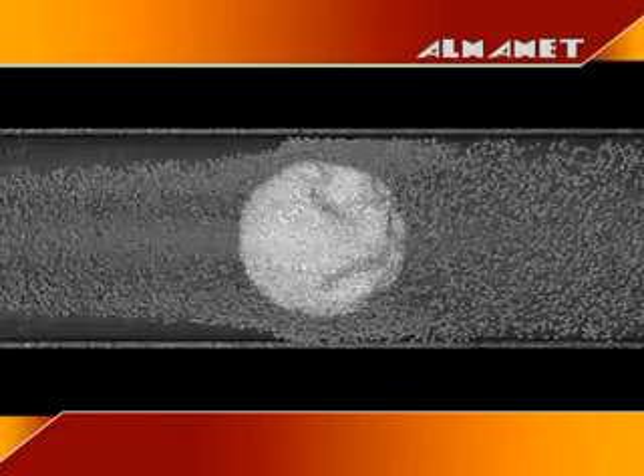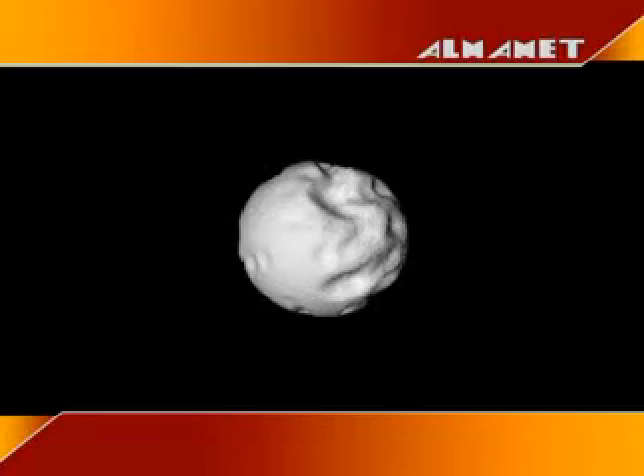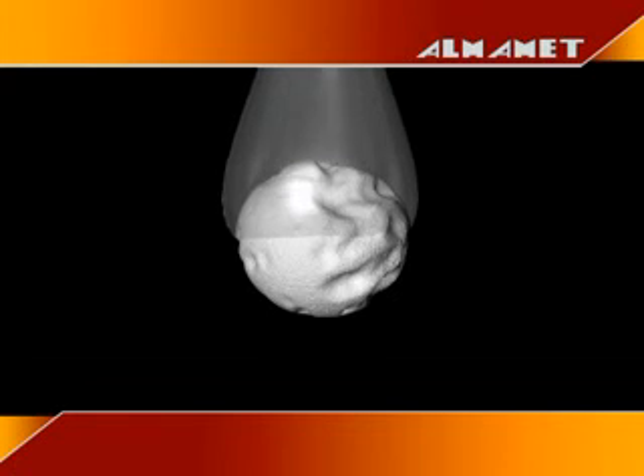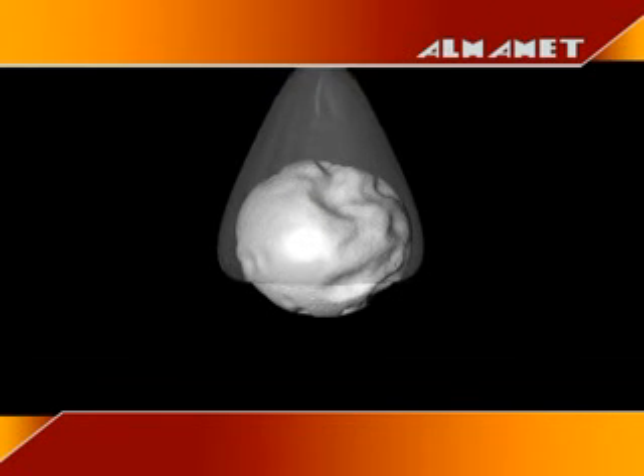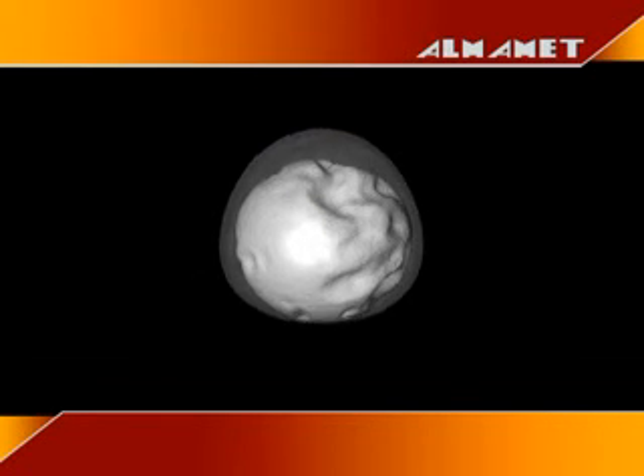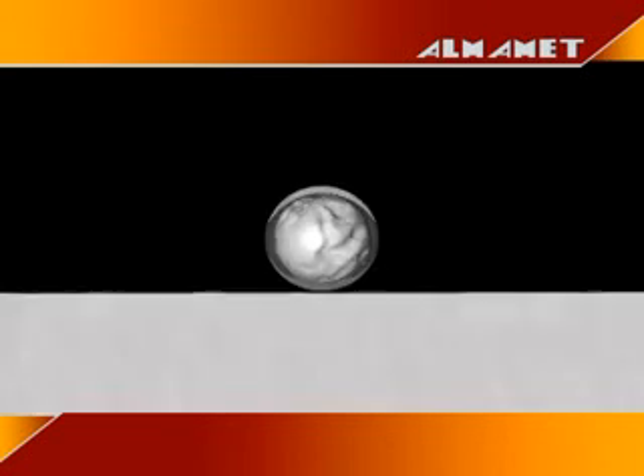To essentially eliminate adherence, and thus the possibility of clogging the pipes or lance in the steel plant, Almamet applies a fluidization process to all burnt lime products. During fluidization, the granules receive a specially developed silicone coating that results in flow properties similar to liquids.